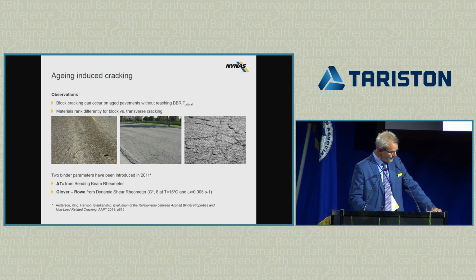And in 2011, there was a paper published by Mike Anderson, and they looked at some of these phenomena, where after a few years, cracks and raveling started to appear on the asphalt surface. And they tried to link that to the rheology of the bitumen. Two parameters have been important in that research. One parameter is called delta TC, and the other, which Professor Pellinen has already mentioned, is the Glover-Rowe parameter. I will focus in my presentation on delta TC, but I will make a little mention of the Glover-Rowe parameter as well.